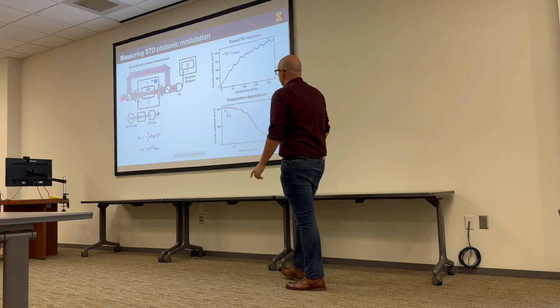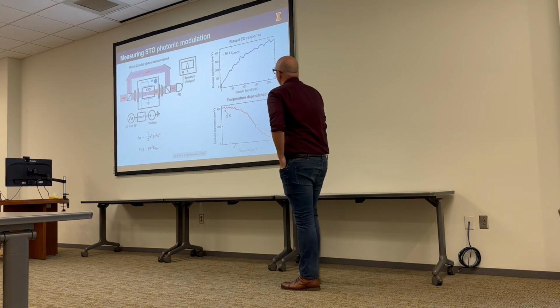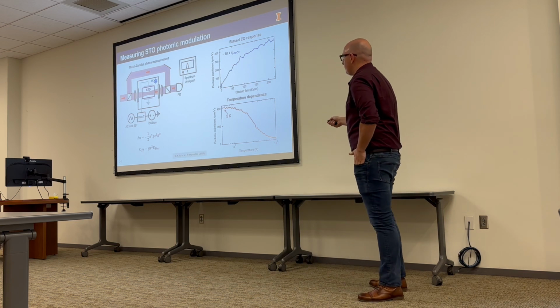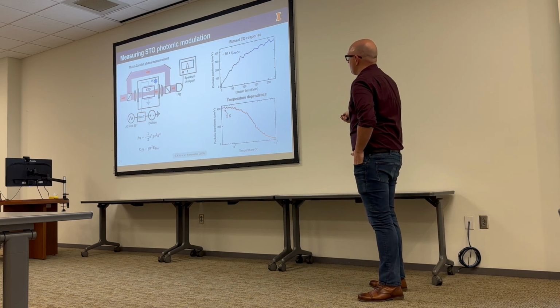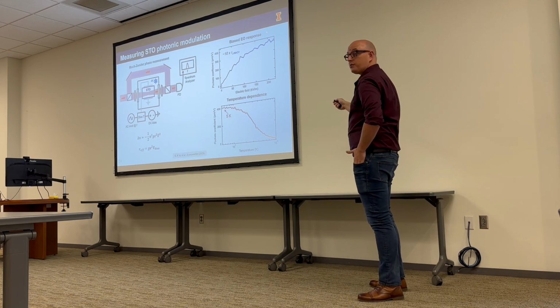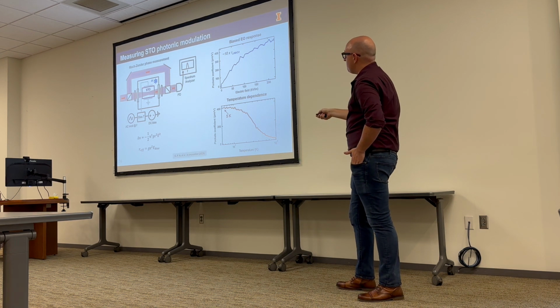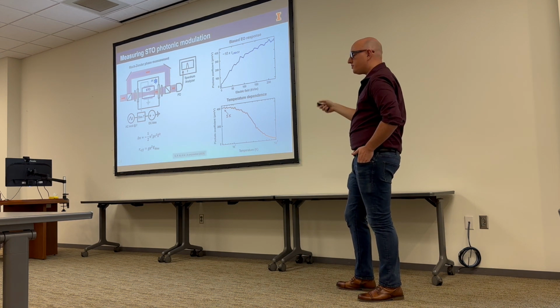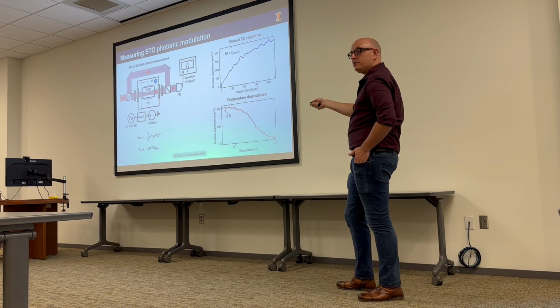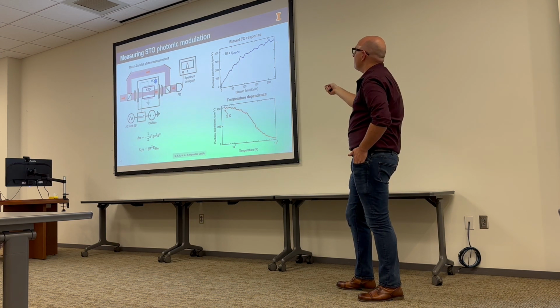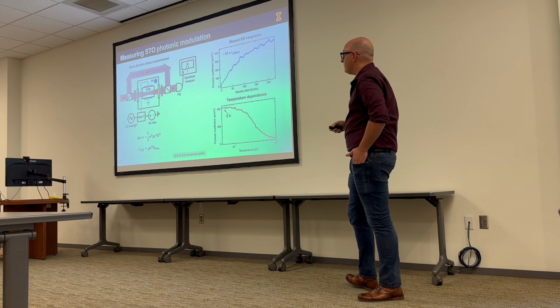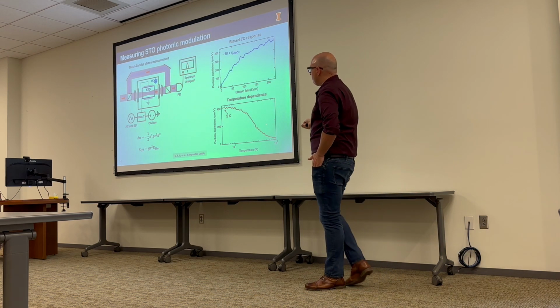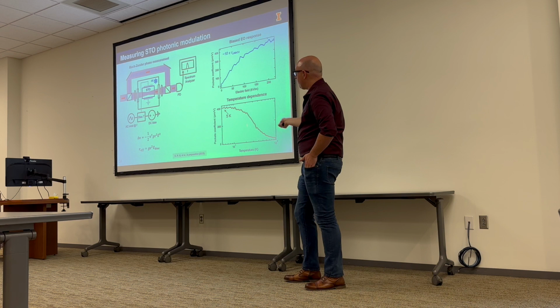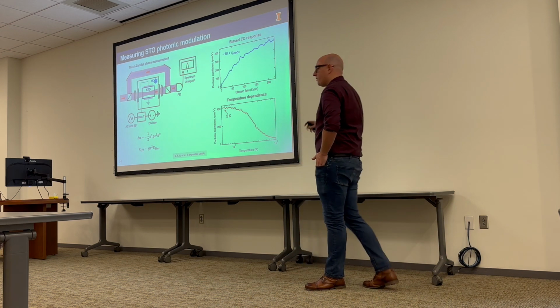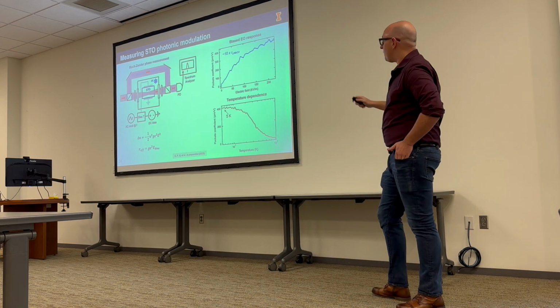We can go and measure this response, and indeed, with 0 applied bias, nothing happens. We apply more and more bias, and the nonlinearity grows and grows and grows. And already with a bulk crystal, 1 millimeter, applying just a regular DC power supply, we're seeing nonlinearities that are at least 10 times greater than what lithium niobate has. It shows this temperature dependence, right, where below 10 to 20 K, it's high. So it has this quantum paraelectric temperature dependence.